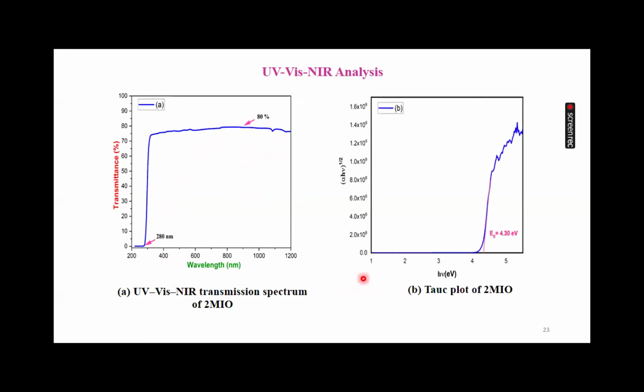As per the Tauc plot drawn, the optical bandgap energy was obtained by extrapolating the linear plots of alpha hν and hν shown in the figure, whereby the bandgap energy was evaluated to be 4.30 electron volt because of the exceedance of wide bandgap, high laser damage threshold, and larger transmittance region. The crystal is a good fit for the application of optoelectronic devices.